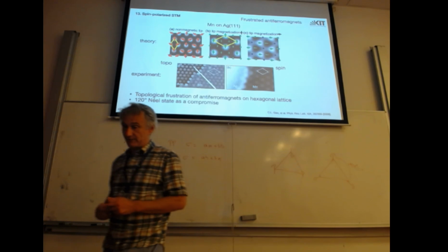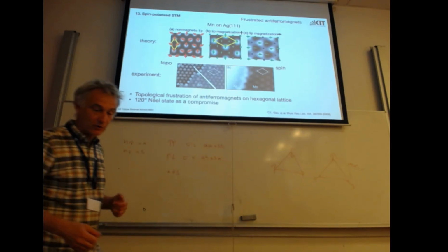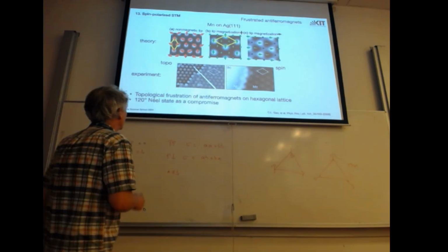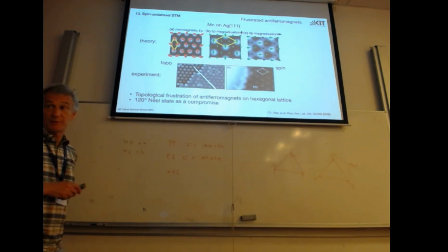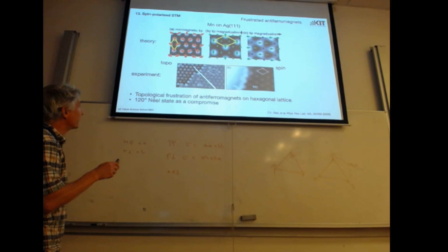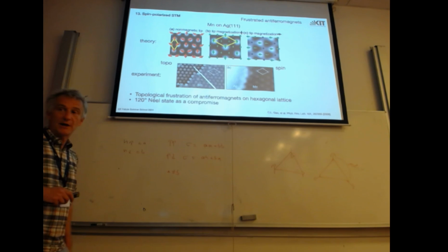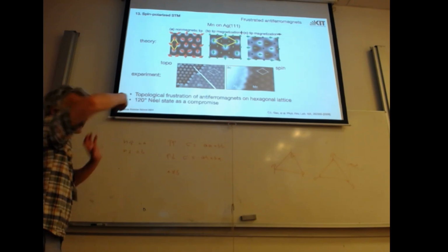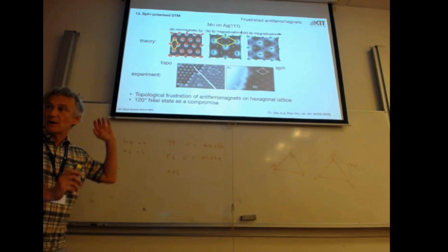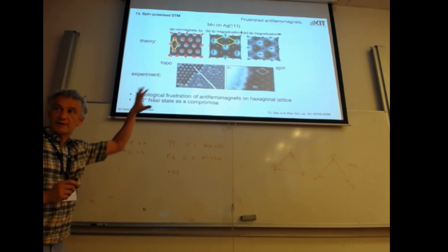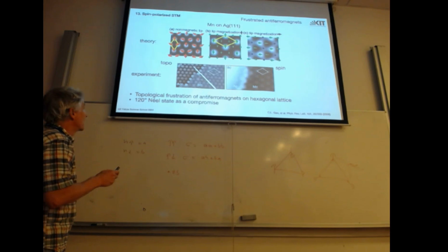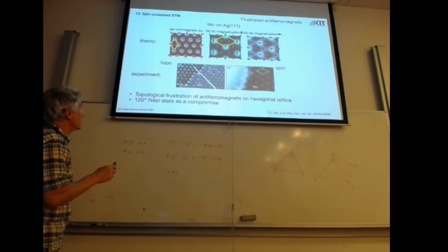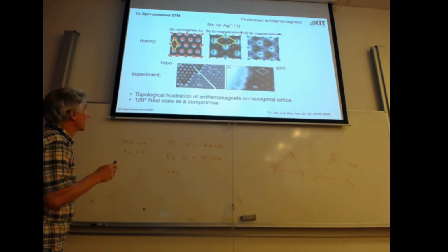That is like this, like you have one between the neighboring spins. So if you construct this unit cell, that's this one. One of the possible unit cells. I plot these magnetization vectors, so each neighbor has 120 degrees. Okay, there are many solutions for this. In principle, you can rotate all of the vectors together by an arbitrary angle, and it stays the same exchange interaction. But you notice that the unit cell now, this is the one atom unit cell, and this is the magnetic unit cell.